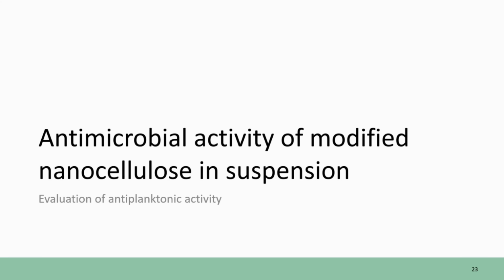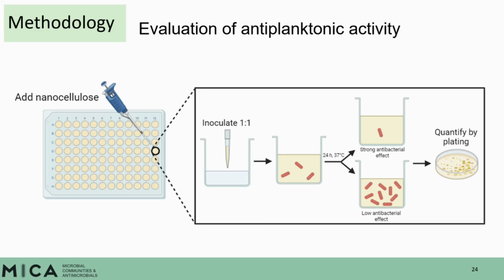So for the evaluation of the antiplanktonic activity of the modified nanocellulose, we use this protocol. In a 96 well plate, we add our functionalized nanocellulose, then we add our bacterial culture in a 1-to-1 ratio, 100 microliters of nanocellulose, 100 microliters of bacteria. We incubate for 24 hours at 37 degrees, and then depending on the activity of our compound, if it has a strong antibacterial effect, we see killing of bacteria and reduction in the number of cells. And if it has a low antibacterial effect, we see growth of cells and increase in the cell counts. And this is quantified by plating and comparing to the growth control where bacteria grow normally.